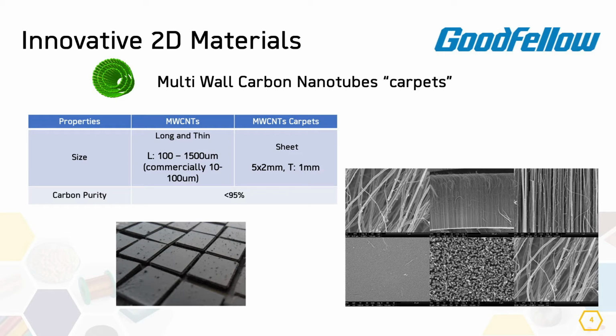The length of our carbon nanotubes can go up to 1,500 microns. They are in the form of a sheet, and you can see the macro picture there, and then also some SEM or TEM pictures of a cross-section of these. These multi-wall carbon nanotubes are chemically bonded with sp2 bonds, an extremely strong bond. This feature, combined with carbon tubes' natural inclination to roll up together via van der Waals forces, provides the opportunity to develop ultra-high strength, low-weight materials with high electrical and thermal properties.